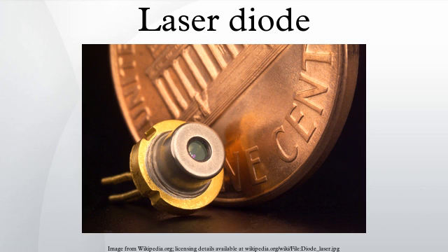But it so happens that the atomic states at the cleavage plane are altered by the termination of the perfectly periodic lattice at that plane. Surface states at the cleaved plane have energy levels within the band gap of the semiconductor. Essentially, as a result, when light propagates through the cleavage plane and transits to free space from within the semiconductor crystal, a fraction of the light energy is absorbed by the surface states where it is converted to heat by phonon-electron interactions. This heats the cleaved mirror.